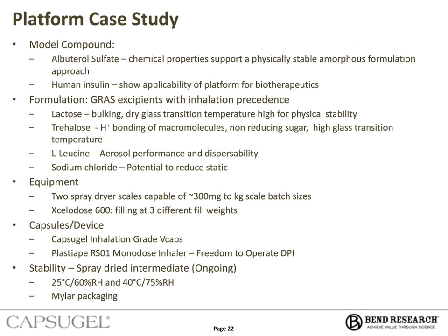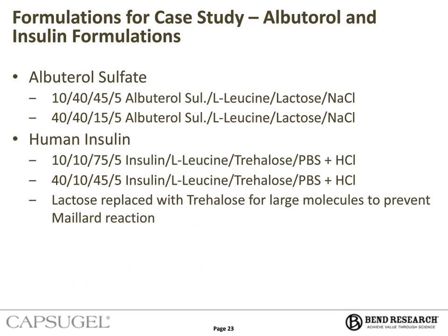So for each of the actives we selected for this, we looked at two different active loadings, so 10 and 40%. And those are chosen to show the applicability of the process to a wide range of active loadings as well as dose ranging options that can be achieved through this platform. So in the two cases, albuterol sulfate, it's different ratios of active loading to lactose. In the case of insulin, it's different ratios of active loading to trehalose. So in this case, lactose was replaced with trehalose for the large molecules to prevent the Maillard reaction.